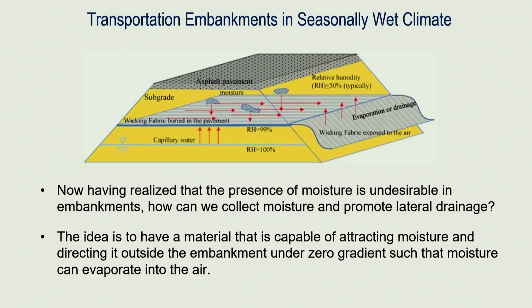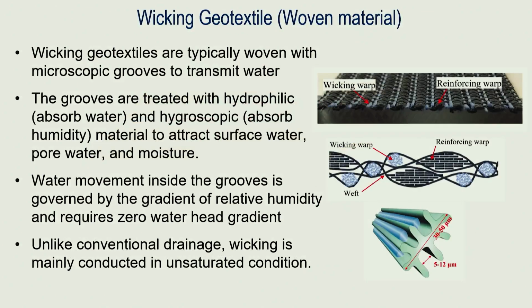This is a cross-section of one of those products that are available nowadays. This is woven material. It's a wicking geotextile. And what you see here is a cross-section that shows how this material is made. It's basically grooves that are treated with hydrophilic and hygroscopic material to attract surface water, pore water, as well as moisture. And you see in the cross-section here, we can kind of zoom into these yarns to try to understand how they work. There are specific channels that have been created such that they not only attract water, but also attract humidity as well.